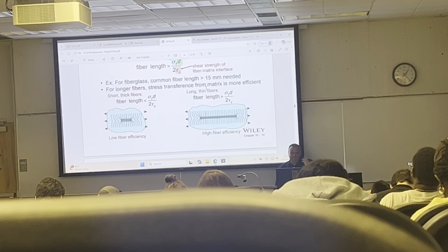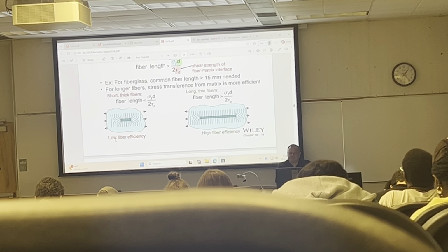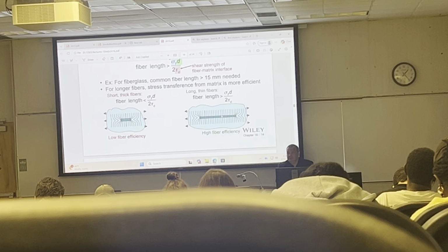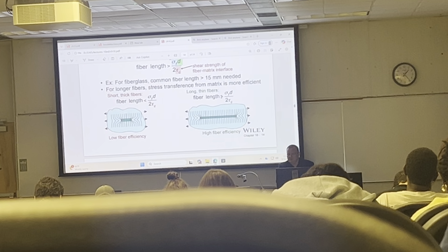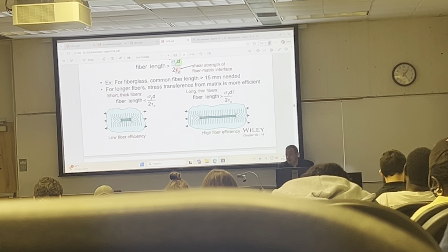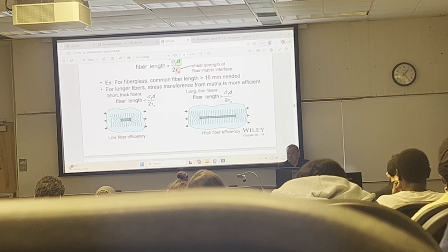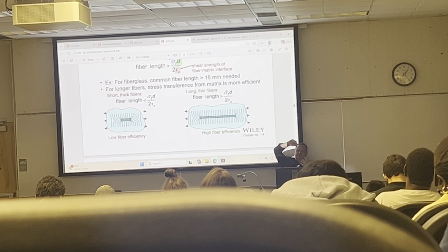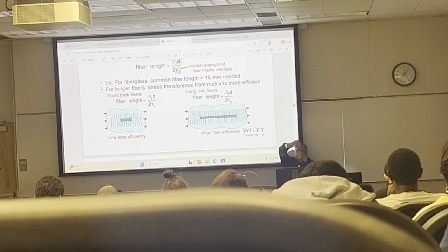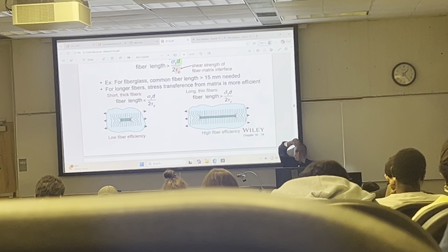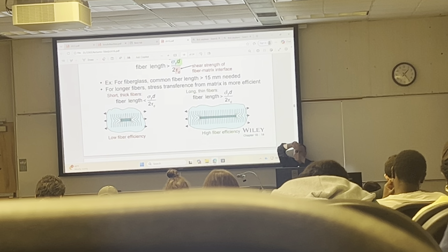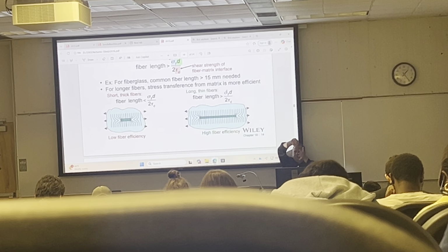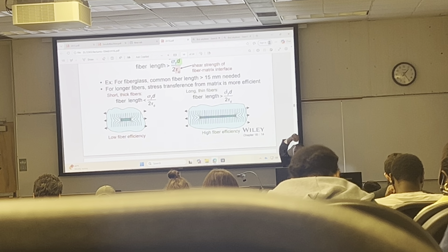So here the stress is applied horizontally, and you can see that this fiber is bonded to the matrix here. So this effect, for the long fibers, is when the fiber length is greater than the strength of the fiber times its diameter divided by the shear stress. The shear stress would be the amount of stress that would be required to take a single fiber and shear it in the matrix, like this. Because the fiber is bonded to the matrix, you're not allowed to do this. And if you do, then it's a failure.